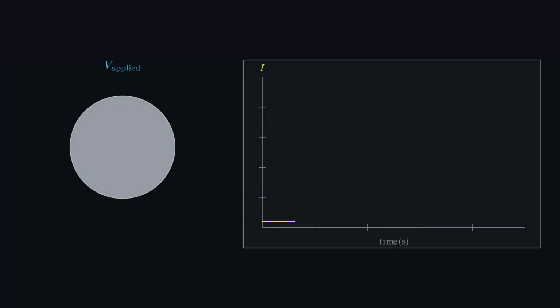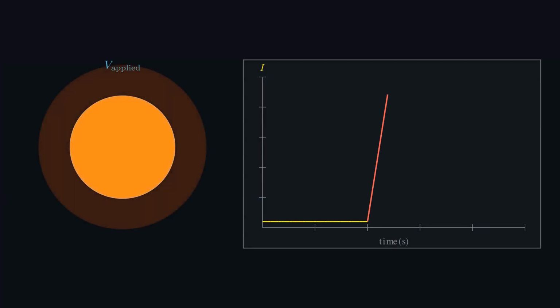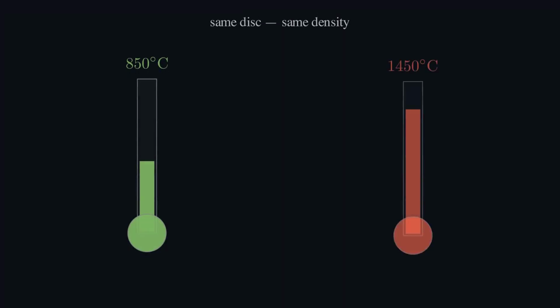In 2010, 3 researchers at Boulder watched a ceramic that normally takes hours at 1450 degrees turn solid in under 5 seconds at 850. One voltage, one small disk, a current trace that nearly tripped the supply. By the time anyone could blink, the puck had shrunk, the trace had plateaued, and the timer had stopped. The result was so impossible that for a year, other labs assumed the experiment was wrong.